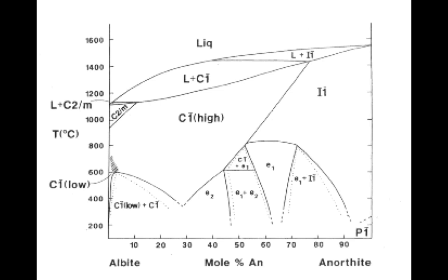As the temperature is lowered, you go from liquid to structurally disordered phases, that's aluminum disordered in the silica tetrahedron, and then as you drop temperature, it re-equilibrates to ordered arrangements or low feldspar structures. So our samples spanning across here, first of all, range within the albite C-bar1 range of structures, and these are principally low albite,